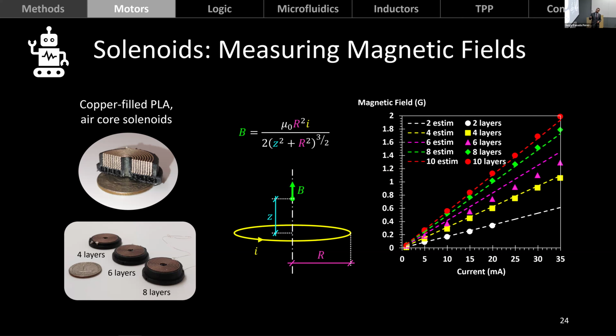Actually, we get magnetic fields that rise linearly with the injected current, and they also rise sublinearly with the number of layers. This is also to be expected because as we add more layers, they contribute to the magnetic field, but they are farther away from the measurement point, so they don't contribute as much.